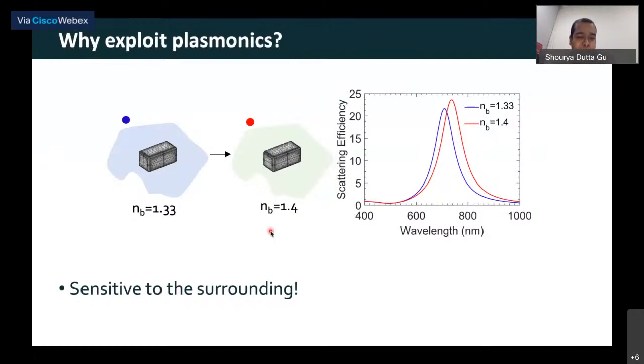And if I change that water medium to something, let's say water plus glucose, the refractive index will increase and go to 1.4. Now, when this happens, if you look at the resonance with the same geometry, the same structure, everything, you will see a shift. The blue one corresponds to the case when it was water, and the red one corresponds to the case when the background was water plus glucose. So you see this shift. By looking at this shift, we are able to say what the change in refractive index is, and thereby go back and say how much glucose is there in the water. So this is the simplest sensor that you can make using plasmonic structures.